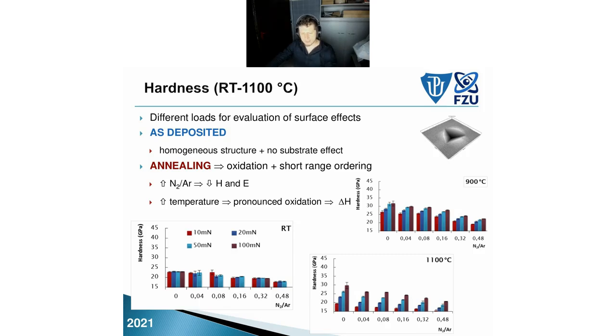After annealing, we can see an increase of hardness in all samples in general, but with surface effects. Shallow indents show a lower hardness than deeper indents, which means there is something happening on the surface, unsurprisingly, the oxidation layer. This effect is more pronounced in the 1100 annealing in air. This is annealing in air, so we can see this oxidation layer effect be much stronger. But apparently, this whole system has higher values, at least at 900 degrees Celsius, which means there is an increase of hardness, an increase of mechanical properties due to short range ordering, but also surface effects due